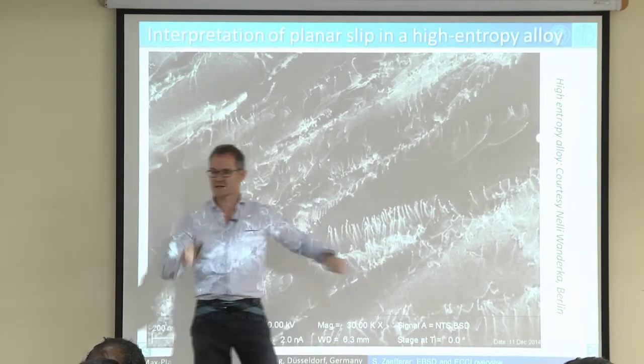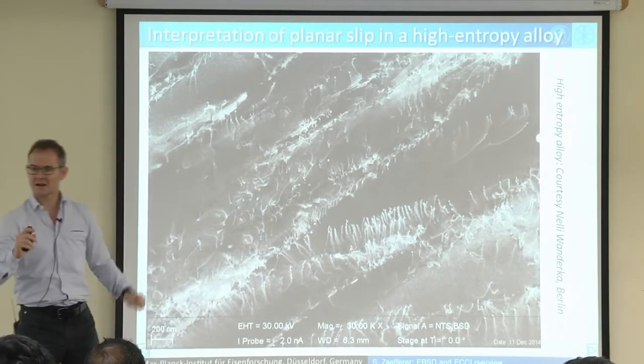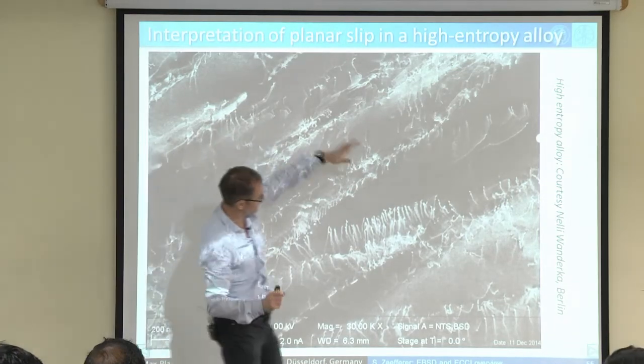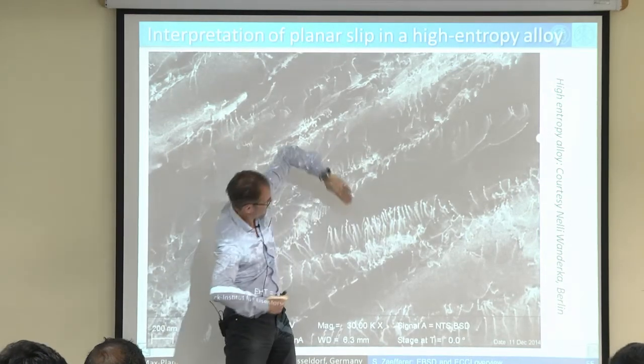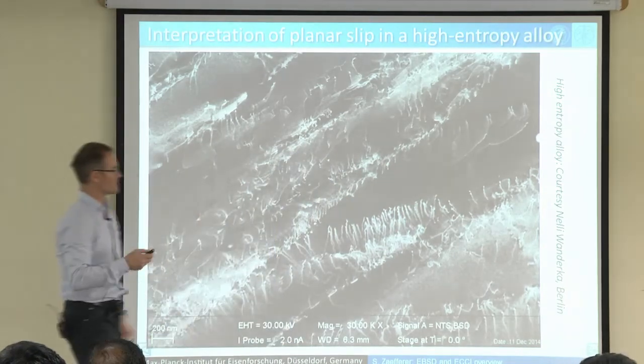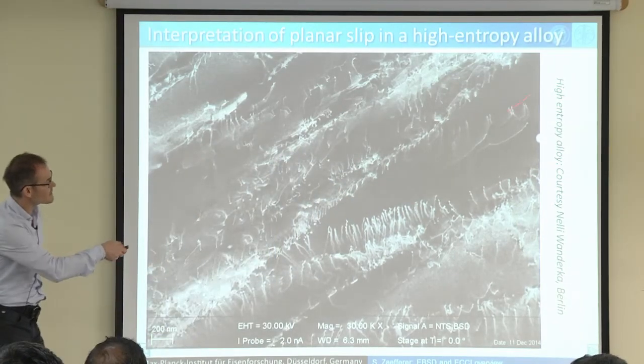Bright, dark, bright, dark, bright, dark. Typical for TEM images as well, and appears due to the fact that this dislocation is not parallel to the surface, but inclined with respect to the surface. You see it here as well, you see it here as well.